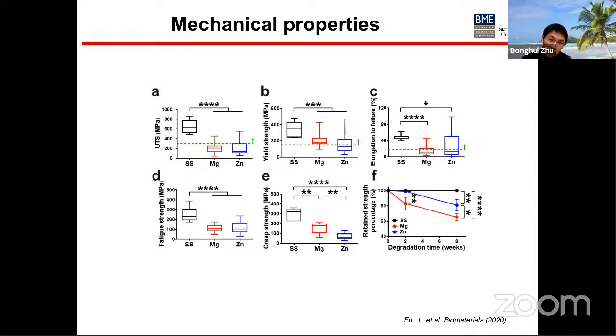On the other hand, magnesium and zinc have similar tensile and fatigue strength, and magnesium has slightly higher creep strength than zinc. The elongation rates of zinc show a discrete distribution with average value between stainless steel and magnesium. Overall, all three materials can meet the minimal mechanical strength required for a stent material, although magnesium and zinc may need some alloying strategy or mechanical thermal deformation treatment to further enhance their mechanical properties.